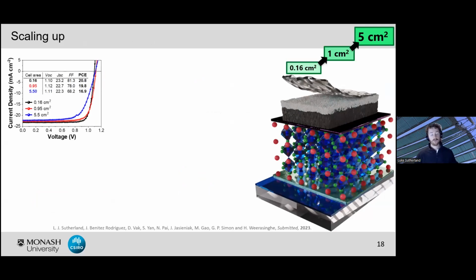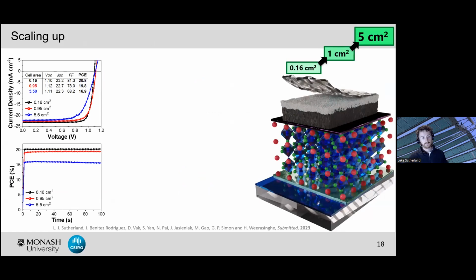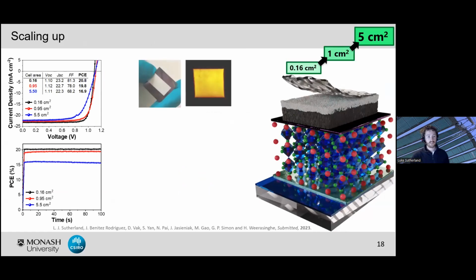And we were able to push these limits and achieve up to 19.8% for a 0.95 centimeter squared cell and 16.9% for a 5.5 centimeter squared cell. Now, all these devices exhibited good stabilized efficiency.